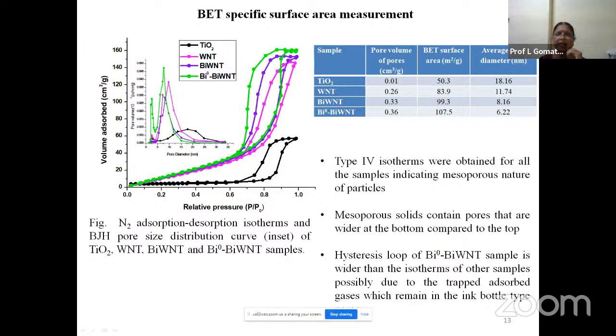And here, this table gives different details about the surface area measurement. The pore volumes were also calculated, and the pore volume keeps increasing. That means the material becomes more porous for Bi0 BiWNT, and the surface area has also increased because of this porosity. We can see 107.5 meters square per gram, and the average pore diameter is in this range. As I mentioned, the hysteresis loop for the Bi0 BiWNT sample is wider than the isotherms for the other samples, possibly due to the trapped adsorbed gases which remain in the ink bottle portion.